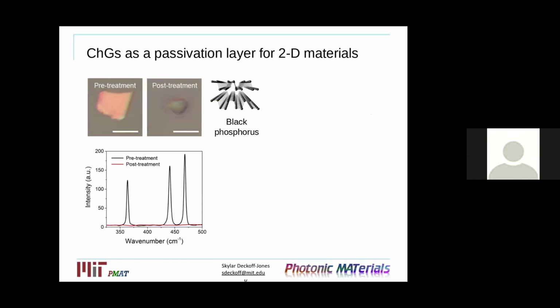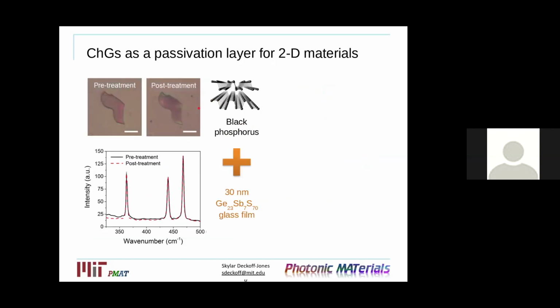And furthermore, we look at actually using the chalcogenide glass as a passivation layer. So because black phosphorus is quite reactive, it oxidizes very easily. However, if we put chalcogenide glass on top of a flake of black phosphorus, we see that it can actually prevent the black phosphorus's oxidation and damage, even from a thin layer.